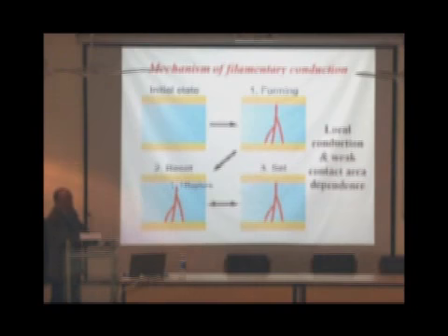When you apply the set voltage again, the filament forms again and you go to the set voltage. So the device is going from the high resistance state to the low resistance state by the formation of these small filaments in the copper oxide.